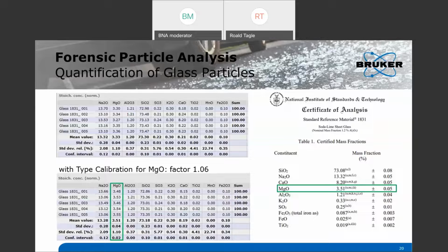For the M4 Tornado, the software gives the possibility to easily create a standard-supported fundamental parameter quantification, where you can adjust the fundamental parameter quantification by using one or even more reference materials and optimize the results so that you get the expected values. In this case, the type calibration factor for magnesium was 1.06. You enter this in the software, and after that, the results of the quantification are quite good.